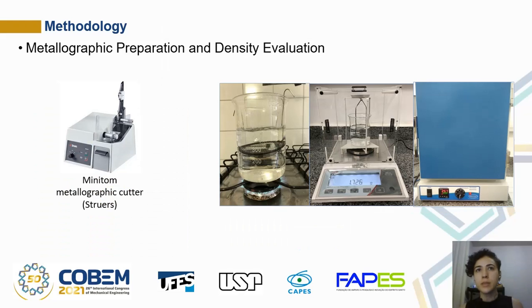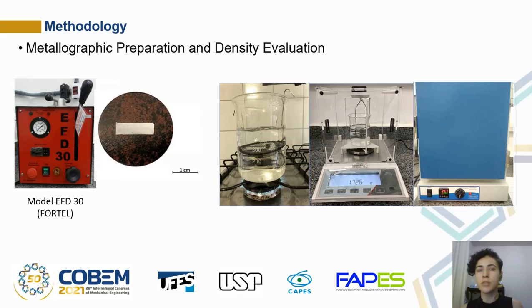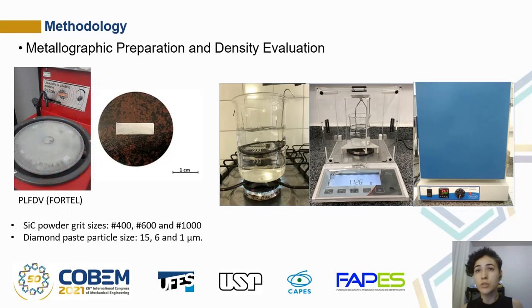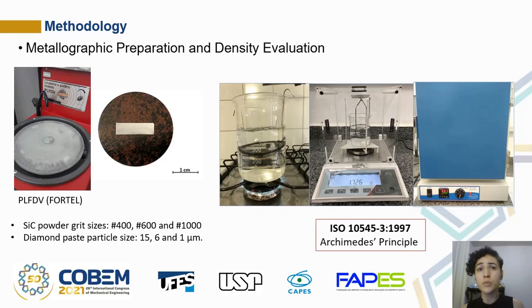The sintered samples were sectioned in half using a metallographic cutter. One of the parts was mounted in a manual compression mounting machine with bakelite to carry out the mechanical properties evaluation. The mounted sample had the apparent surface ground using silicon carbide powder, and then it was polished with a diamond paste. Micrographic images were taken in a scanning electron microscope. The other half part was reserved for density evaluation.